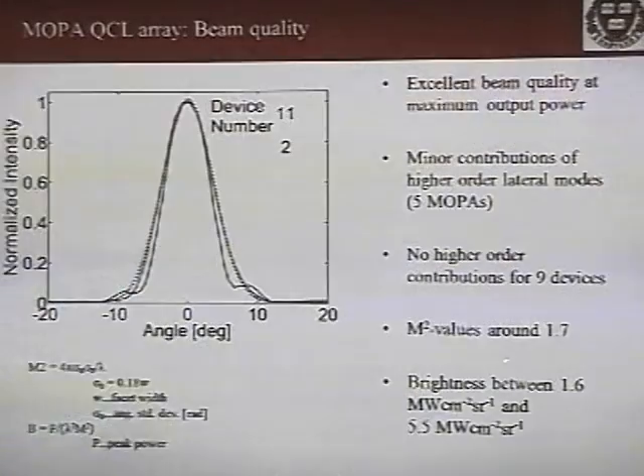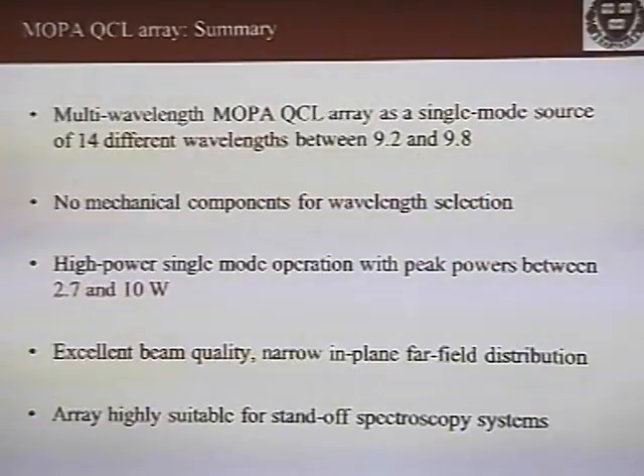And if we look at the far field, the majority of them look actually good. Again, there's a lot of improvement to do, but the direction looks pretty good. They are fairly high brightness. The beam quality is good as a start. I would say it's actually very good. We get an M square of 1.7. Very significant brightness.